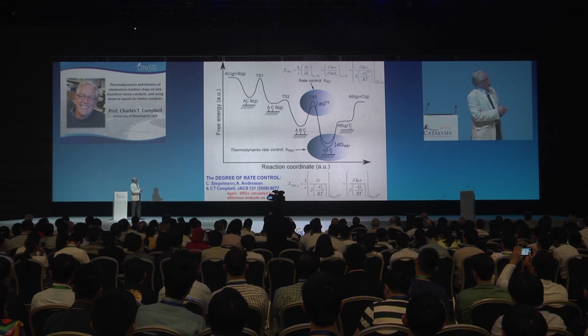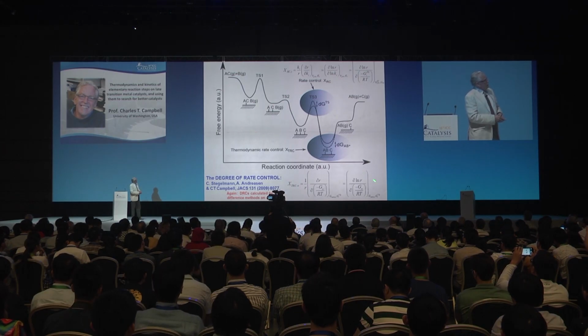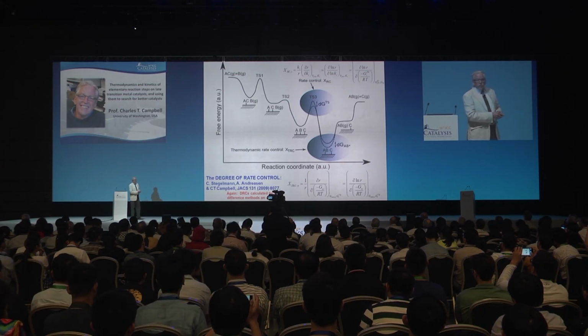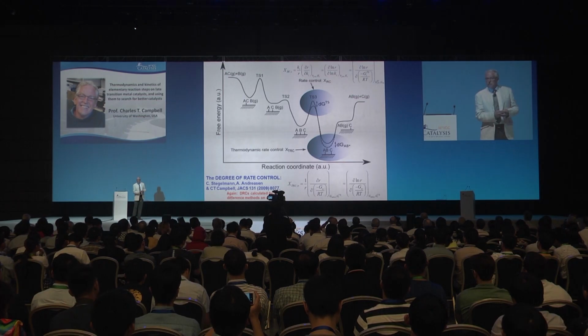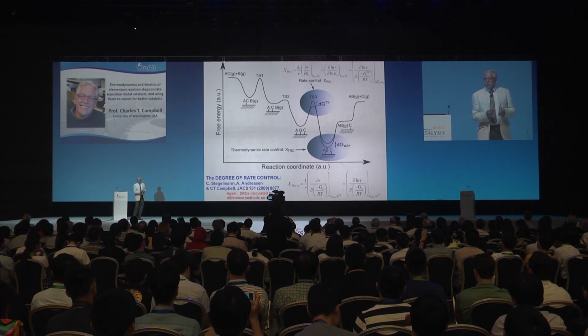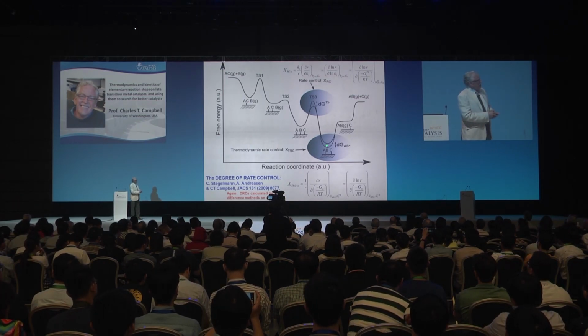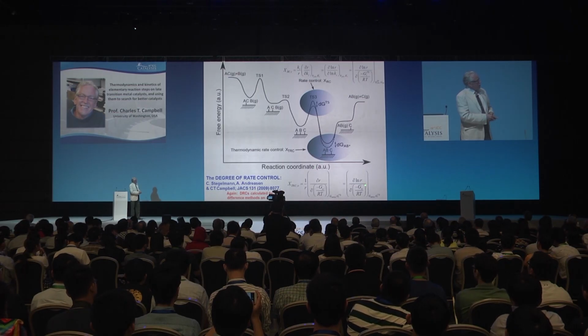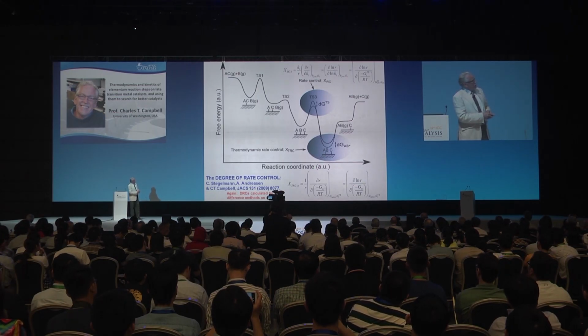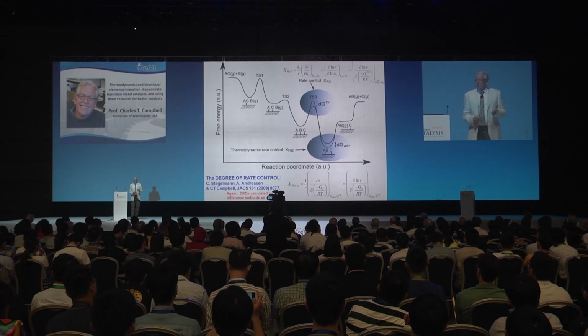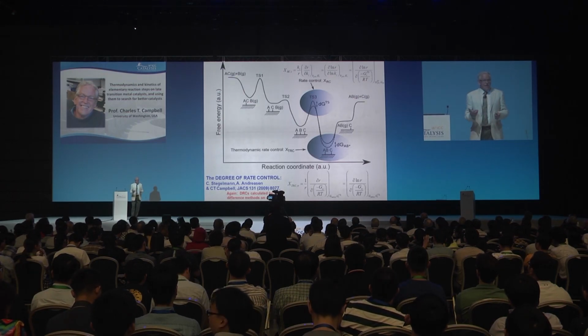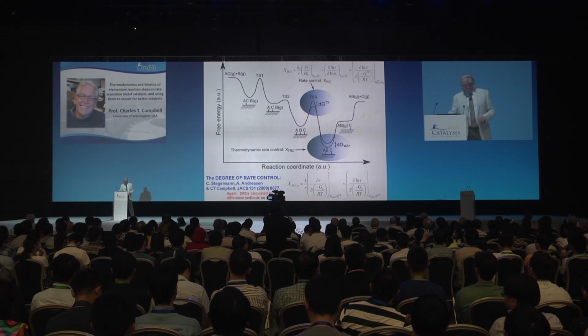When you look at it this way, you realize that you can do the same operation also for all the minima in the standard state free energy diagram for the reaction. And so it's how much the rate increases fractionally per unit stabilization of the adsorbed intermediates. And those things tend to be negative numbers because when you stabilize adsorbed intermediates, it actually poisons the net reaction rate.